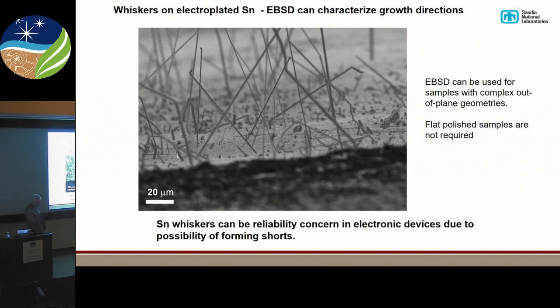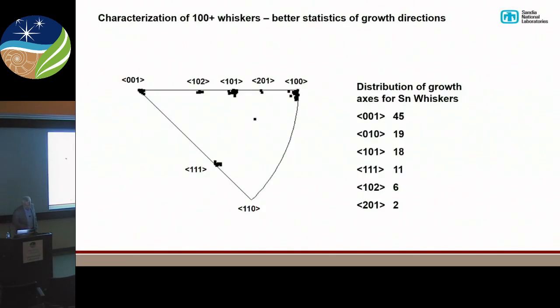What else can we do with EBSD? So we don't have to have a flat polished surface. In the literature, you'll find that tin whiskering is a huge deal with microelectronics these days because we took lead out of solders and then we grow these tin whiskers that can get quite long and cause shorts. There's lots of data in the literature about tin whiskers causing problems in cell phones, cars, and satellites. So it's a big problem. So one of the questions is, how do these things grow? Can we determine that? And yes, of course we can.